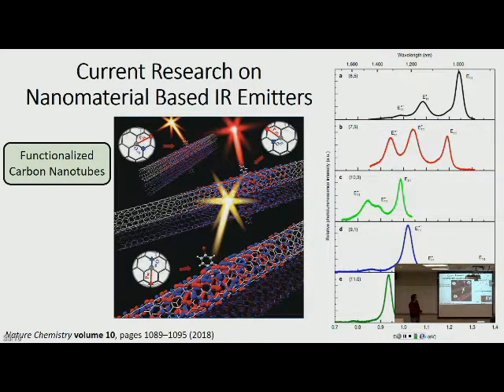And this is from a recent Nature paper that came out of Los Alamos. You can see based on the chirality of the nanotube, so each panel corresponds to a different chirality, and I'm not sure which type of functionalization they used or what kind of dye they put onto the nanotube, but you can tune the emission from 1 micrometer, which is its lowest excitation, to like 1.4 micrometers. So you're still in the near IR range within that tunability anyway. So those are some recent results that have been found for IR emitters.